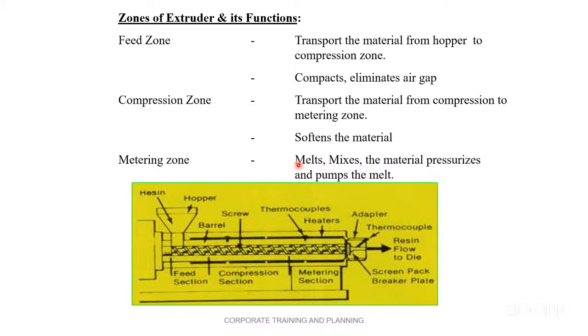Again, in many machines feed zone and metering zone have a higher ratio or a higher length. Generally it is 50, 25, 25. Feed zone has a length of 50%. There are also thermocouples provided here, which help give the actual temperature of the die.